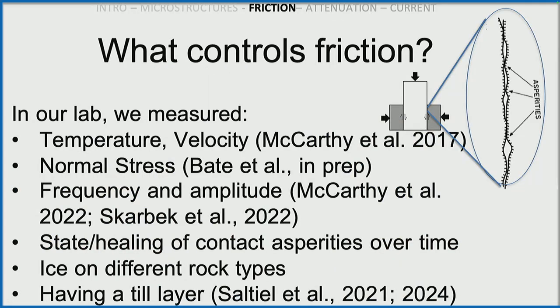Okay, so we've been working on friction in the lab using that biaxial apparatus for a while now, and we've been exploring various parameter space depending on the thing that we're thinking about. I started off thinking about glaciers, so we were working at relatively warm temperatures, minus 20 to almost 0, looking at temperature and velocity dependence with ice sliding on rock. And then we started doing sinusoids of that forcing, thinking about tidewater glaciers that are moving with the tide. They're modulated by the tides.